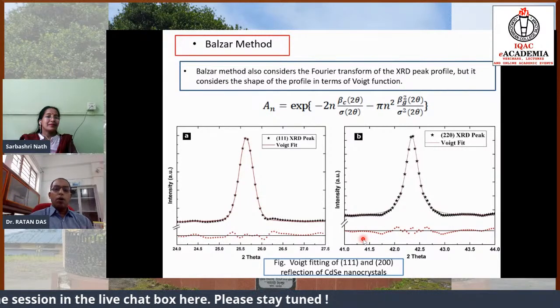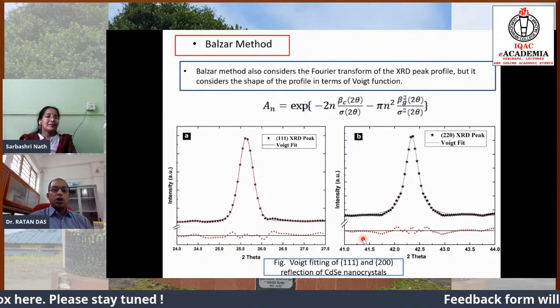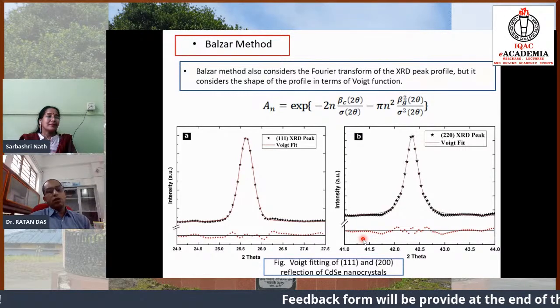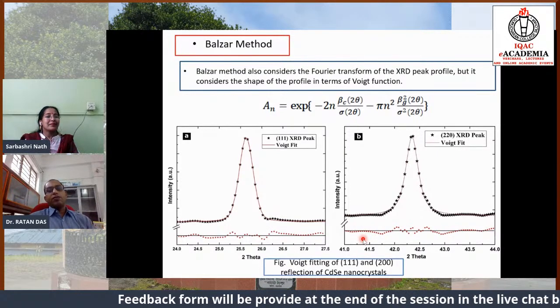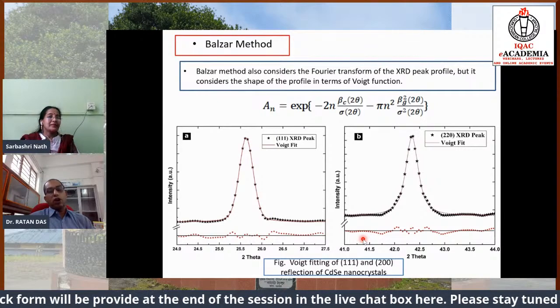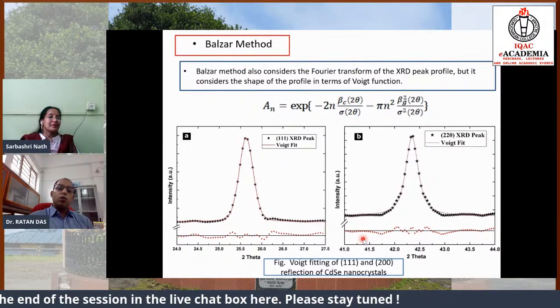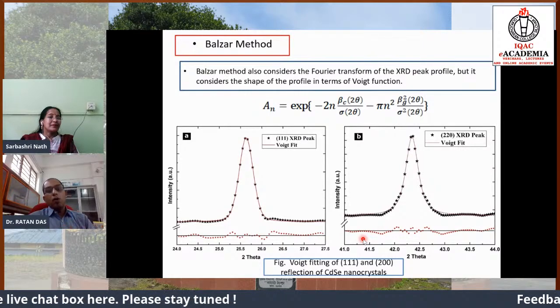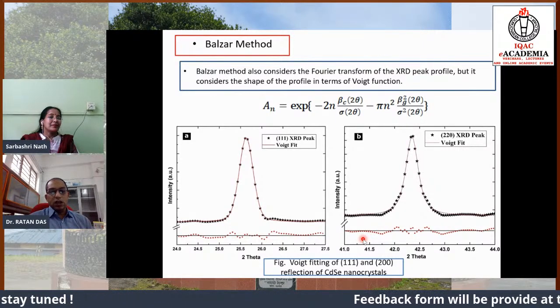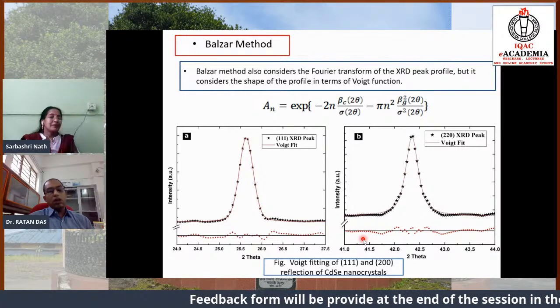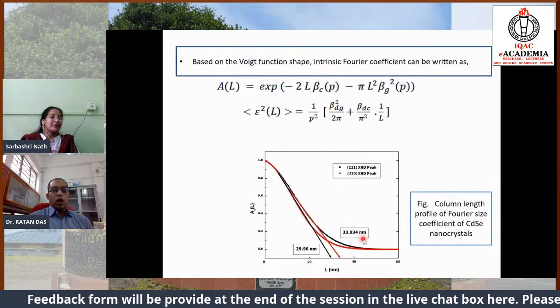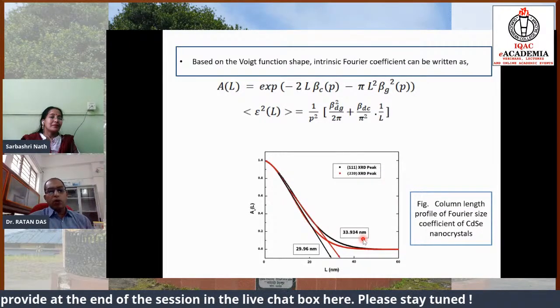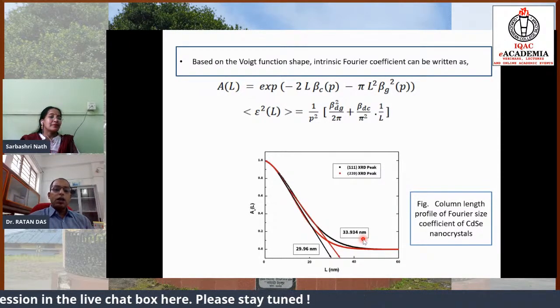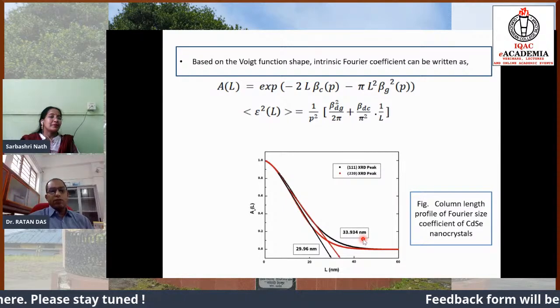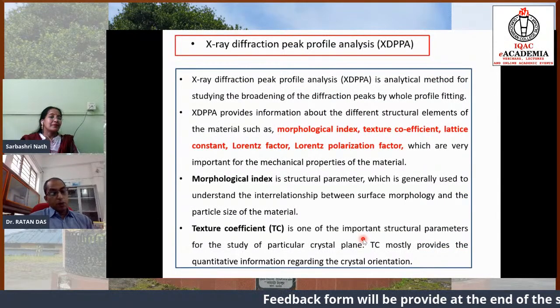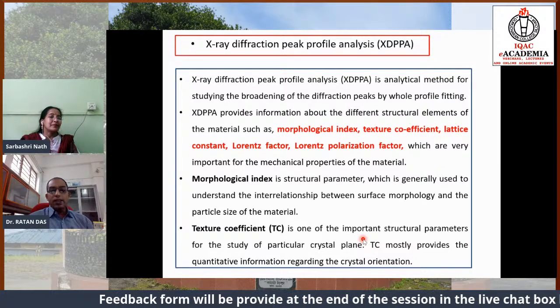And that is another method, what is known as the Balzar method, and it also considers the Fourier transform of the X-ray diffraction pattern, but it considers the shape of the profile in terms of a Voigt function, rather, I can say, a pseudo-Voigt function generally, which fits well in the case of the Voigt method. And again, by using other complicated terms, we can obtain the size and the strain value of the diffraction pattern. So this part is something different regarding the size and the strain value.